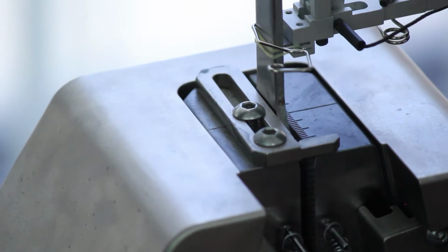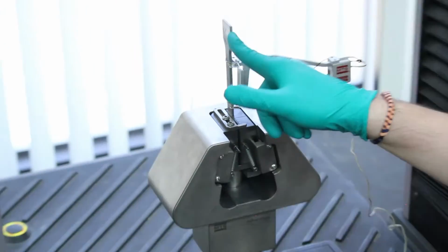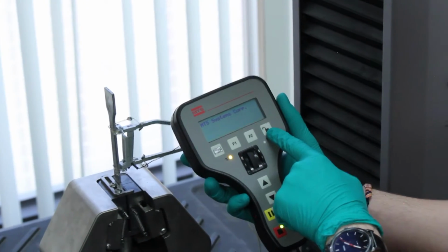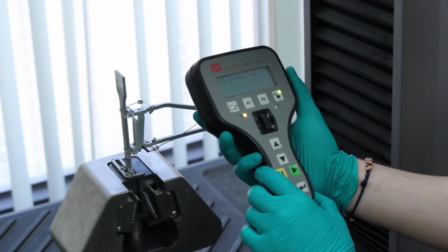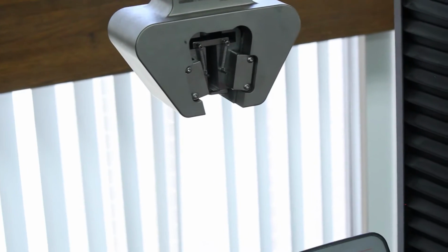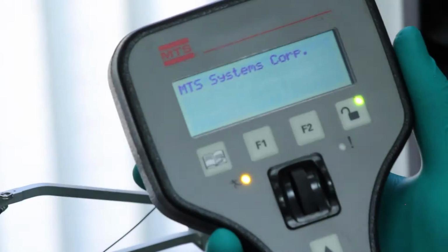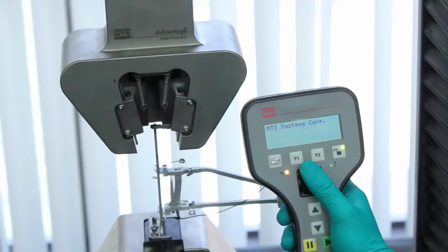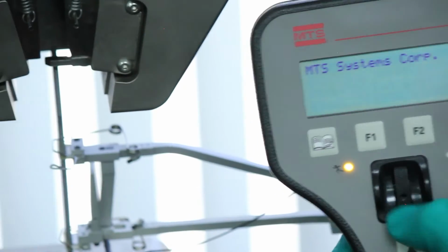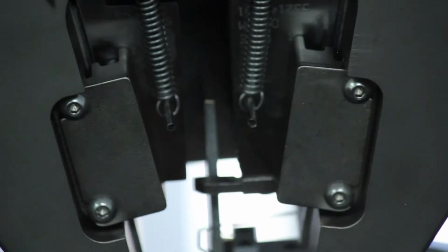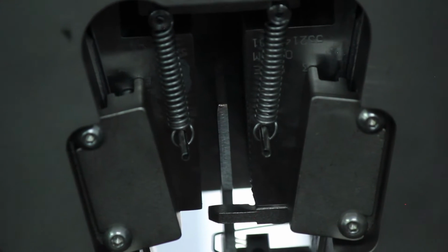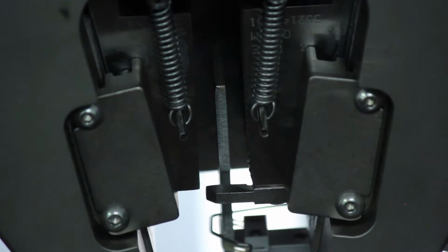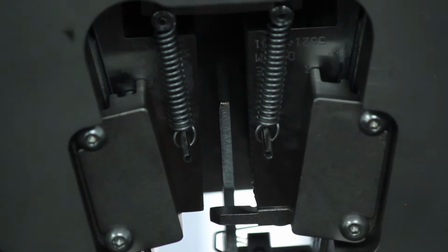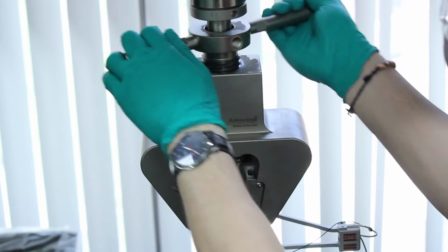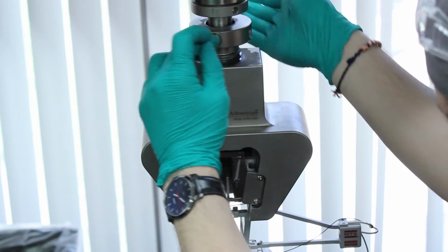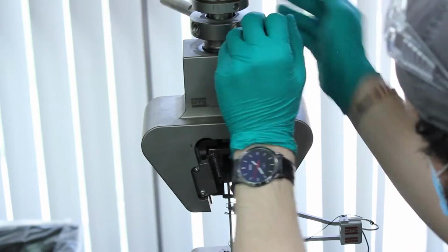Use the turnstile at the bottom to tighten the grip head against your tensile sample. In order to use the frame controller, you must press the lock button on the top right of the controller. Then, you can use the up and down arrows to move the crossbeam all the way down to your sample. The little roller at the top will move the crossbeam in fine amounts, very small, so that you can precisely place your tensile sample into the tester. Again, be sure the shoulder of your tensile sample rests just above the end of the grip head. Same as below, use the turnstile to tighten the grip head against your tensile sample. Make sure it's nice and tight because there's going to be a large load placed on your sample.